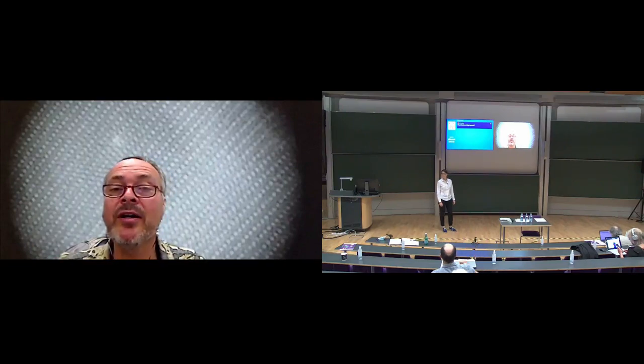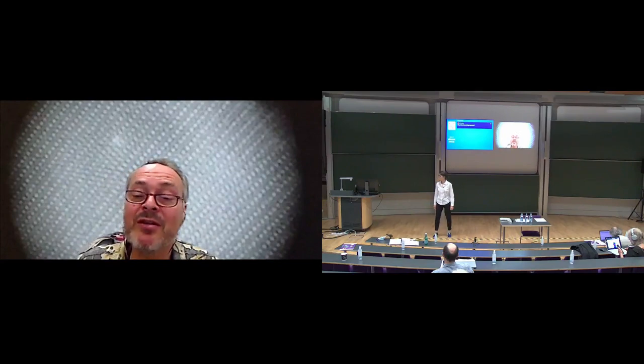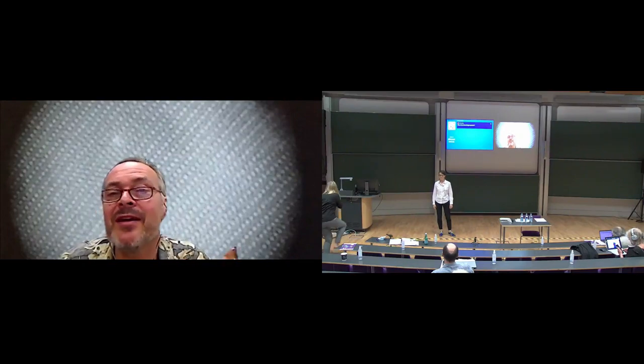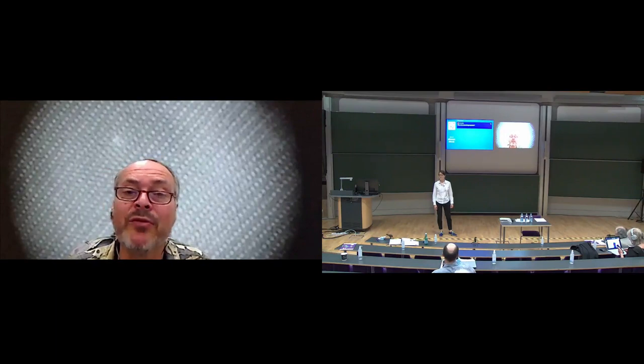So if you want to get glasses or gels, then the slow drying is not so important. But if you want to get to equilibrium, it's now much better established that, for instance, these silica particles of 300 nanometers that were shown in the optical, you really have to dry them for 8 hours or longer. Otherwise, you don't get the icosahedral structuring. So for equilibrium structures to form, the drying needs to be slower than the self-assembly, and roughly the self-assembly scales with the third power of the diameter. So for 300 nanometer particles, this takes hours. For 10 nanometer particles, because that to the third power is quite a lot less, you can probably get away by doing it in a few minutes.